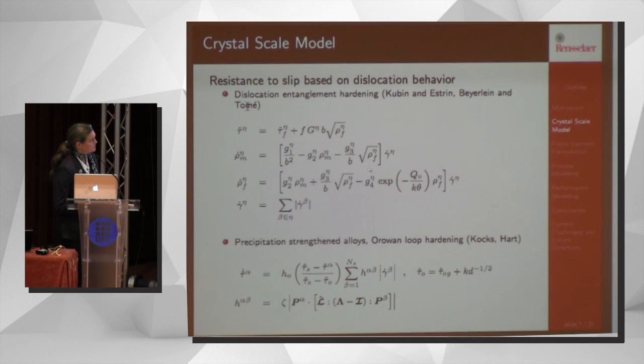And what's interesting, I'm not going to go into the details of the equation right now, but just conceptually what's interesting in the difference between entanglement hardening and precipitation hardening is that in entanglement hardening, the latent hardening, the hardening on the slip systems that are not slipping, is higher or equal to the hardening on the slip system that you're slipping on.